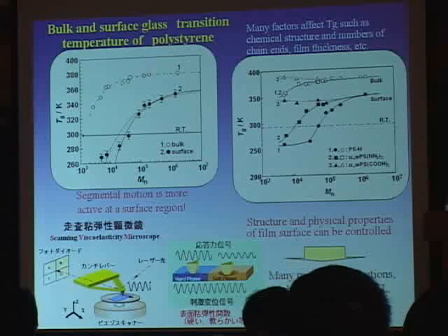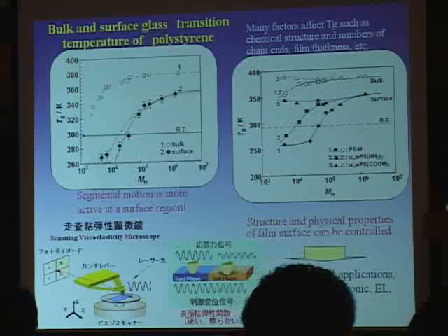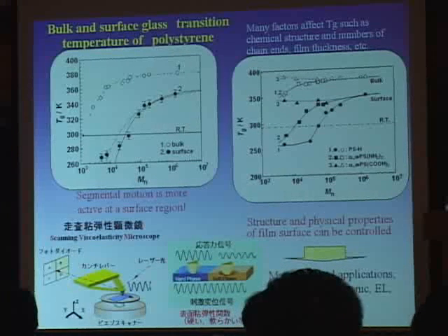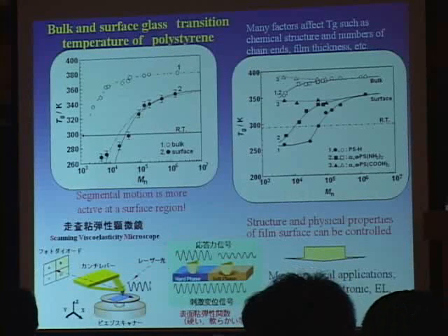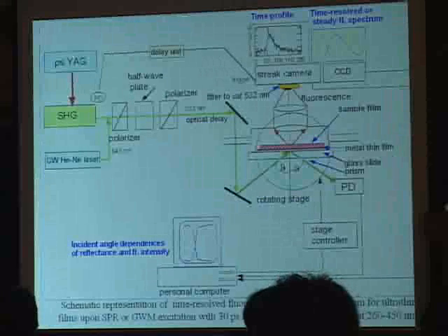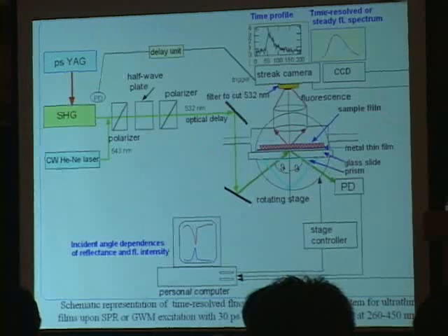So we invented scanning viscoelastic microscopy, and we added a sinusoidal pulse to the surface, and we detected the response as a function of temperature and frequency. This is an example. And recently, we are taking another approach using a non-contact method.